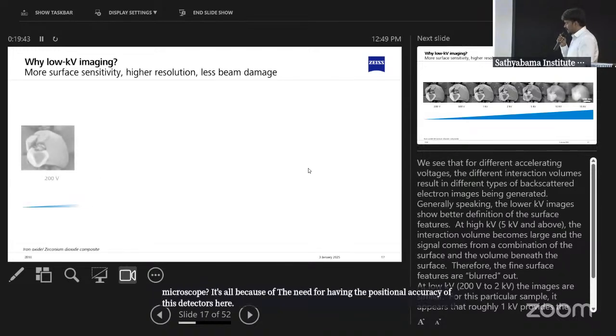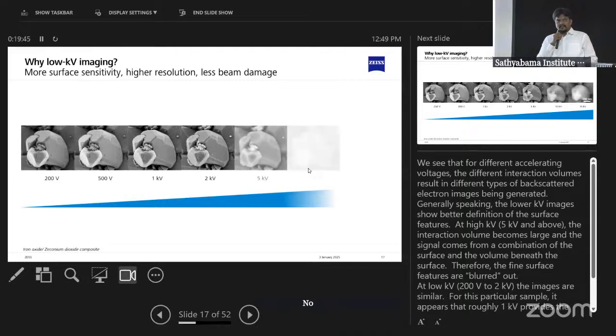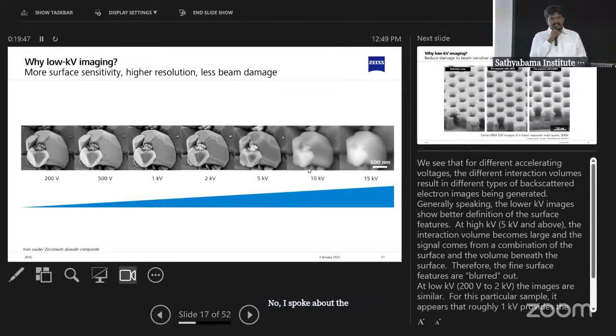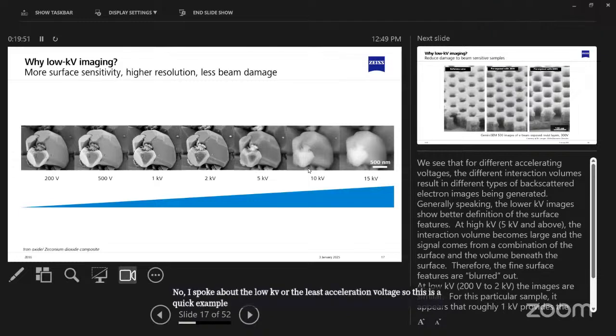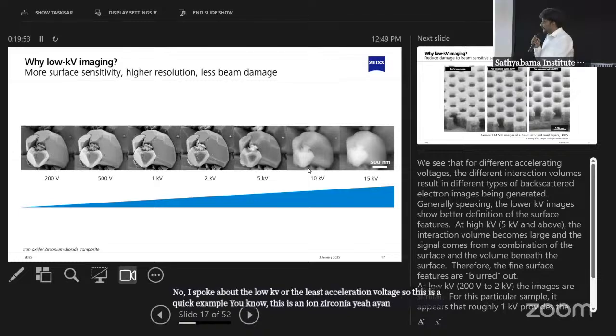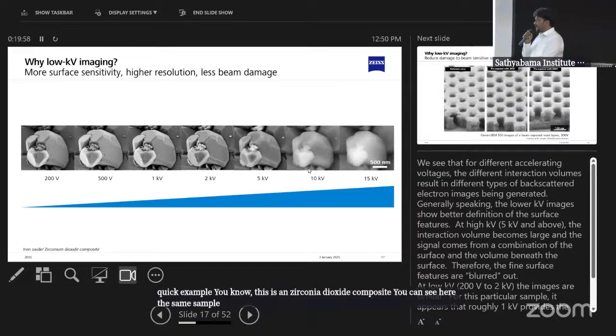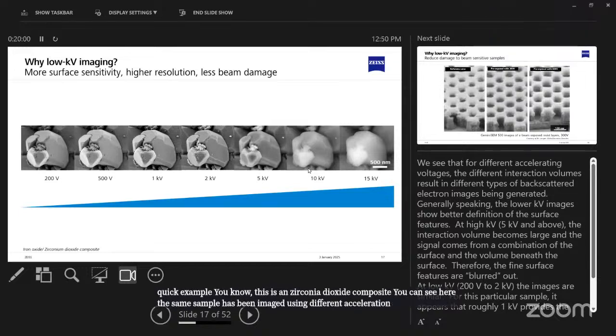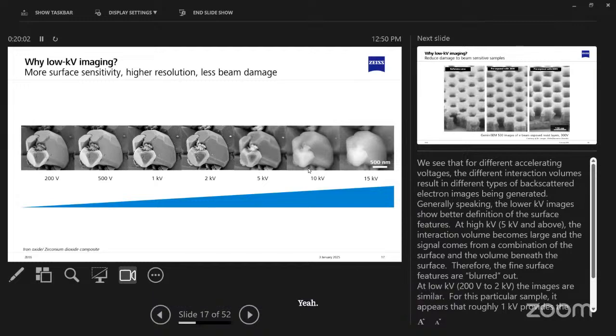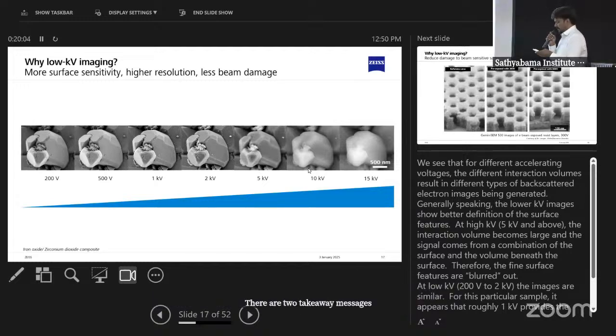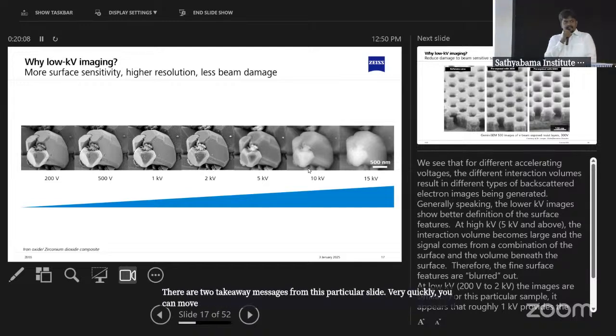Now, I spoke about the low kV, or the lowest acceleration voltage. So this is a quick example. This is an iron zirconium dioxide composite. You can see here the same sample has been imaged using different acceleration voltages. There are two takeaway messages from this particular slide. Very quickly, you can move from one acceleration voltage to the other.